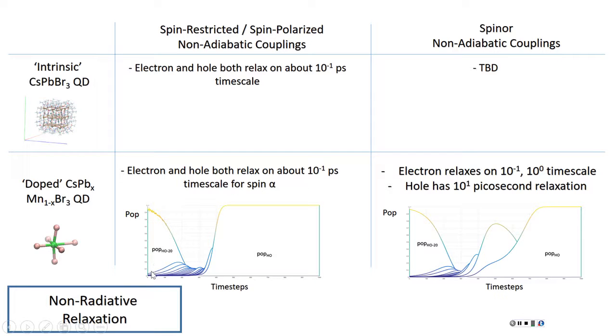You can see that these little things going up, that means that states are gaining occupation. Then when they decrease, they're losing populations, the states below them. You see that happens pretty fast in the conduction band. And even once it hits the dopant states, which are close to the band edge, it takes a little bit of time, but after about 300 time steps, all of them relax to the band edge.